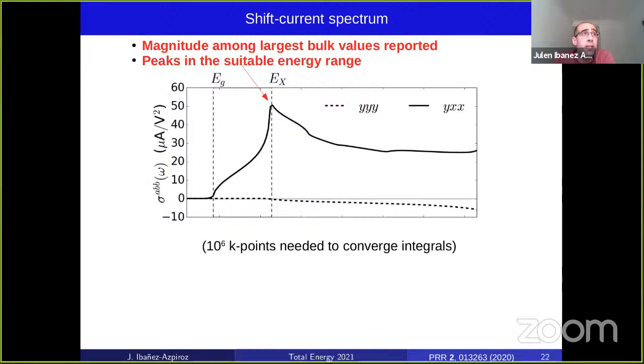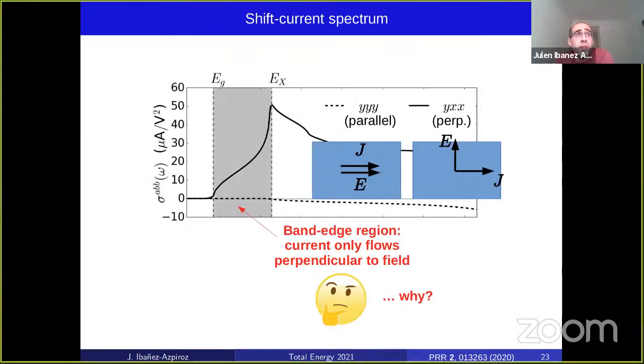But that's about the size. What about the direction of the current? Now, these two components allowed by symmetry correspond to quite different setups. In one of them, current flows parallel to the electric field of light. This is usually the most common setup. But in the other one, it flows perpendicular to the field. And if we focus on the bandedge region in the gray area, we notice that only the perpendicular component is finite. The parallel one completely vanishes. So why is this? Why does it vanish even though it's allowed by symmetry? This can be traced back to a quantum dipole selection rule associated with mirror eigenvalues, as we will show next.